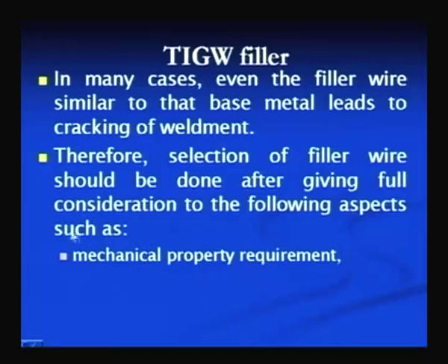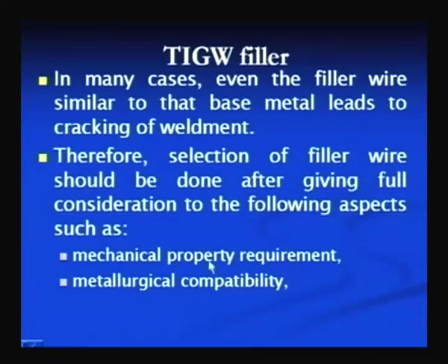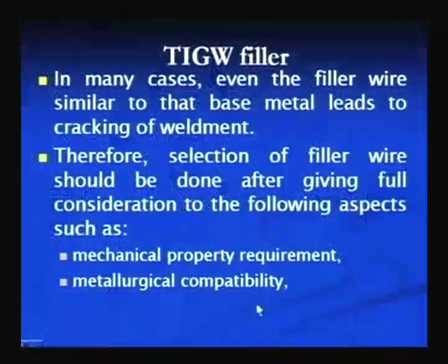The joint produced must provide the strength or the other mechanical properties required to perform the desired function by the weld joint. So, the filler metal must be able to provide the weld metal which can take the desired load or which can perform the intended function. The metallurgical compatibility is also important, because sometimes dilution changes the composition of the weld metal, and that leads to some of the problems like solidification cracking, or mismatch in the thermal expansion coefficient between the different metals or between the base metal and the weld metal can also lead to problems